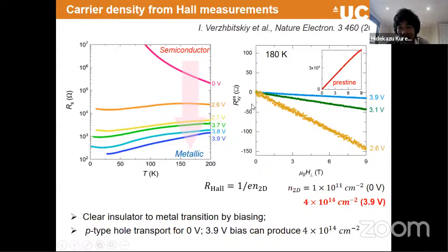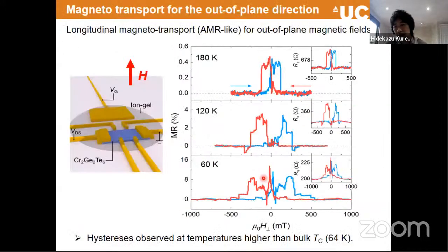On top of it, by using a Hall bar device, we can calculate the carrier density by using the slope of Rxy versus the out-of-plane magnetic field. By using this slope, we can extract that in the zero voltage regime, this is a very, very small hole-doped behavior. But when we dope electrons heavily, at about 4 volts, then we can achieve a large carrier density. So that's great because we turn insulating CGT into conductive CGT so that we can use the magneto-transport as a probe of the magnetism.